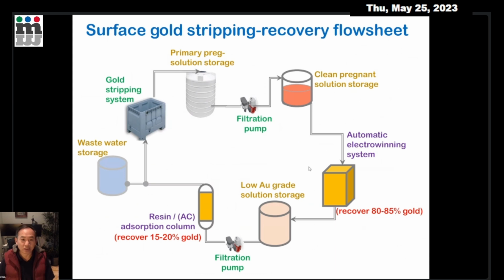And here is the simplified flow sheet, covering only the surface gold stripping recovery. As I said, the gold stripping system here, the first blue one, I don't know if you can see my mouse. And then the pregnant solution comes to the storage. We have a filter and clean the pregnant solution, and then deliver it to the automatic electrowinning machine to recover gold directly. From this step, we can recover at least 80 to 85% of the gold.